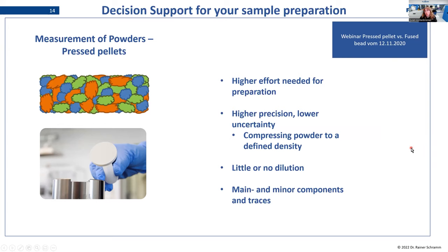So for the preparation of pressed pellets, you need a higher effort than just for the cup, because you maybe have to mix it with a binder, and then you have to press it to get this nice pressed pellet out of it. But the higher effort comes with a higher precision and a lower uncertainty. Why is that? It's because we are compressing the powder to a defined density here. A big advantage of this preparation technique is that we need little or no dilution. So we just need a little bit of binder, or maybe even no binder if my sample can bind by itself. And this means we have no large dilution, so we can measure main and minor components, but also traces.